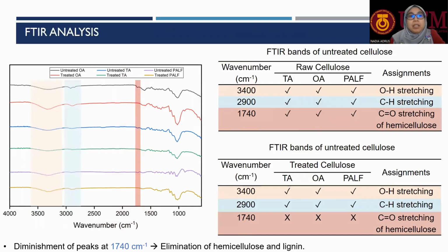Here is some chemical functional group analysis via FTIR, where we can see the wave numbers of the respective spectra for untreated versus treated fibers. We compare OA, TA, and also PALF. Here we see that the diminished peak at 1740 is an indication of the elimination of hemicellulose and also lignin. Here, we can also see the peak assignment of the untreated and treated fibers, given in a summary for you to have a look at easily.